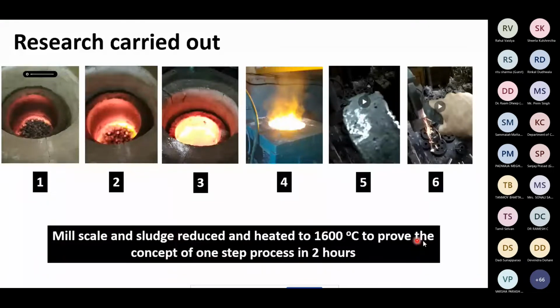So here is the furnace. These are the balls of the sludge and slag, and fluxes are also there. It's slowly heating up, taking up the heat. It's conductive heat, which can be observed over here. And then at the end we can see by spark test, this is the sparking test of this material we have checked. Pure metal only gives this kind of spark with a grinding machine. So this spark is observed.